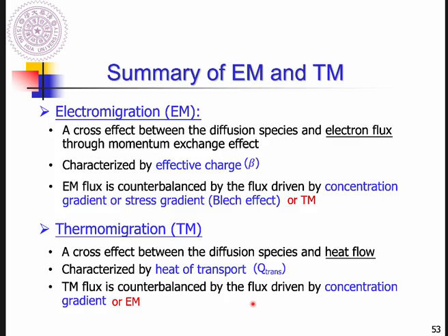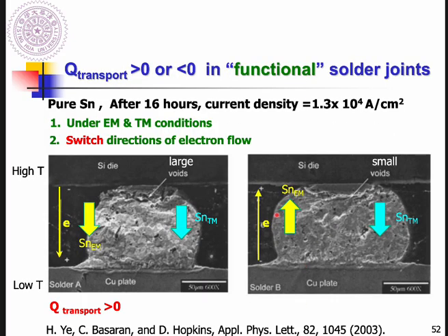So far, I have read lots of recent articles. The new design idea for solder bond is actually to allow the unavoidable atomic flux driven by EM to equal the TM. Then you have a chance to get the flux in quasi-steady state equal to 0, so you can avoid the void, I mean TM or EM induced void, happening or being observed in your solder bond.